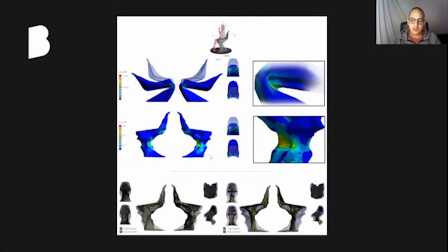The resulting geometry is obviously tested again on the engineering side to see the mechanical properties of the biomaterial in play. And as can be seen, the chair simulated with another 120 kilograms was able to sustain the loads, as the total megapascal stress was on average significantly lower. So it shows that a geometrical transformation of sorts is able to realize these biomaterials in a new geometry that would function well.